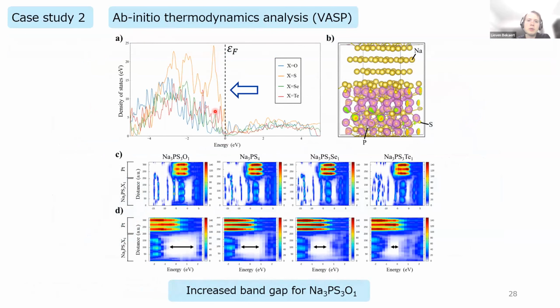You can see that as we move from tellurium to selenium to sulfur and then to oxygen, we move further away from the Fermi level. These are the sulfur 3p orbital energy. So you can see that when using oxygen, you have a lower thermodynamic reactivity towards the sodium metal.